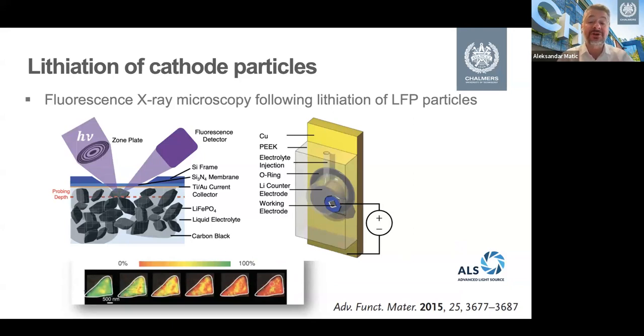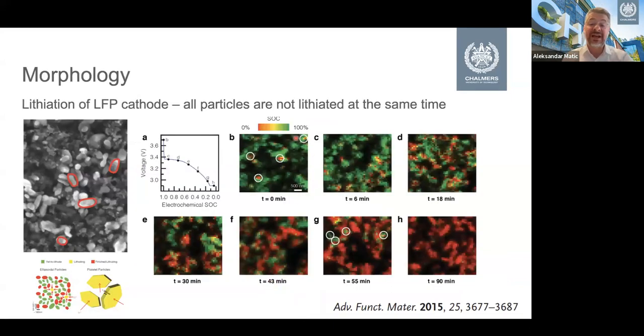And this could be done in a scanning fashion where you could look at a part of the electrode and understand how the particles were lithiated. And you can see that it's not a homogeneous color scheme, which means that all particles do not respond in the same way. In the end, we go to the same state, but you can see that some are faster and some are slower to reach that state. So there is a great inhomogeneity, and this is very important for the engineering and design of the actual cathode and cathode materials.